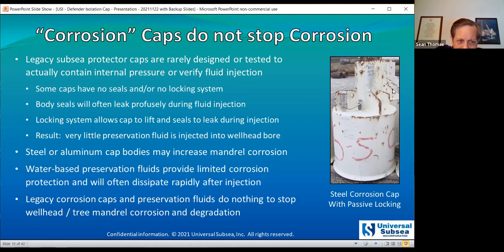Additionally, caps with a steel body or aluminum body may actually increase corrosion of the subsea equipment mandrel that we're trying to protect. Another additional point we'll look at is the water-based preservation fluids that are typically used provide very limited corrosion protection and will generally dissipate pretty quickly after they're injected into the cap. So the result is these legacy corrosion caps and preservation fluids do very little to stop corrosion and degradation of the subsea equipment mandrel.